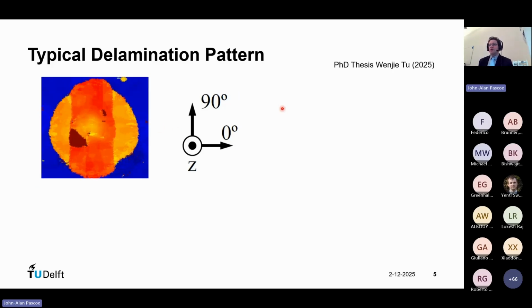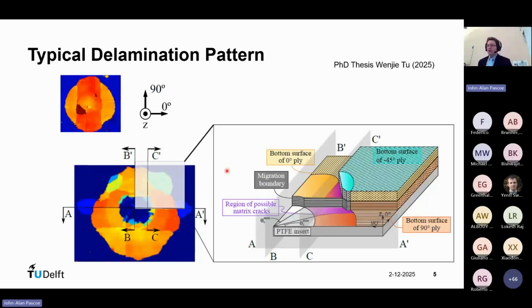And if you have a bit more complex situation, then we get a picture like this. Here's a slightly different layup where we had actually a hole halfway through the laminate, but the same idea holds. So the delamination grows in the direction of the fibers where it can, and if it can't, it immediately migrates until it finds fibers going in the right direction, it grows along those. And in fact, you then even get an additional migration a bit further out in this 45-degree direction.